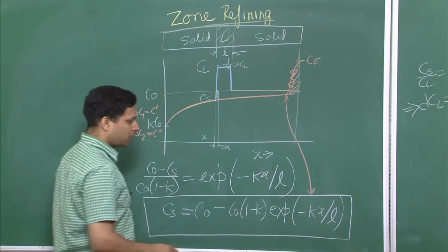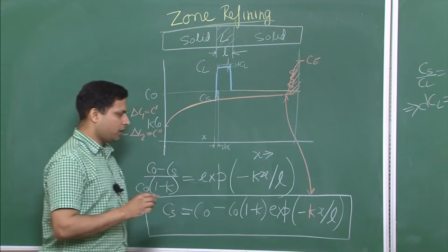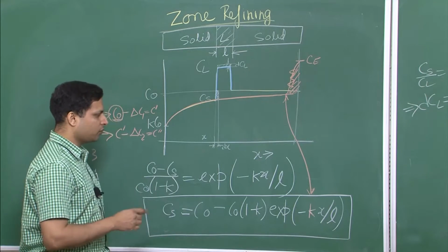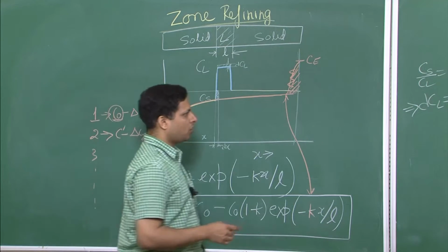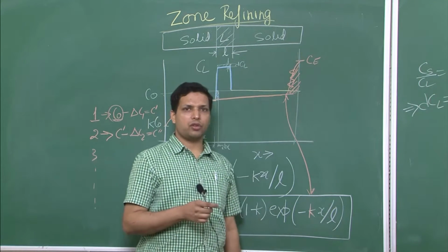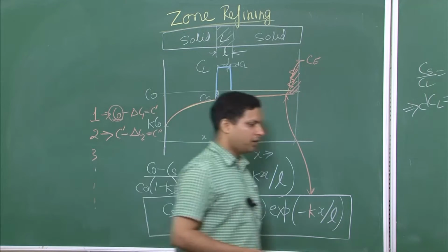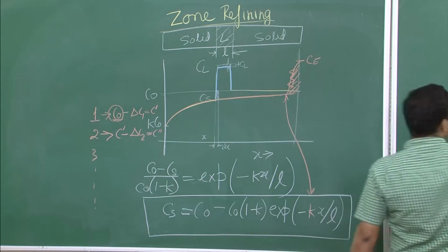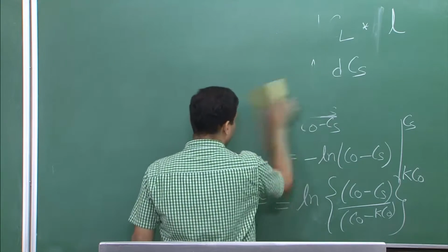And the K value that we have used over here assumes complete diffusion and no convection, but what we can also do is have some amount of convection, in which case we will have to use the K effective value. And remember one thing that I did not explicitly mention about the K effective, but let me put it over here.